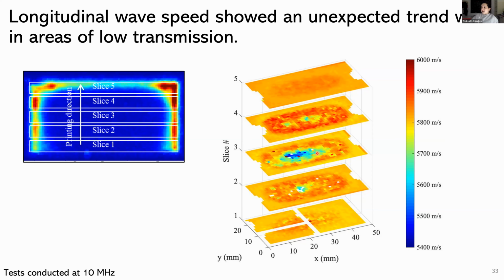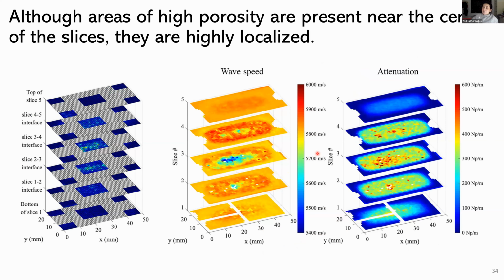So we did a little bit more quantitative analysis of the porosity at the different interfaces. We took the samples and did optical microscopy and sectioned the different pieces, and sure enough, there was a little bit more porosity right in the center, but going from the edge to the middle region of the samples wasn't really supporting that porosity was the driving factor in our ultrasonic response.